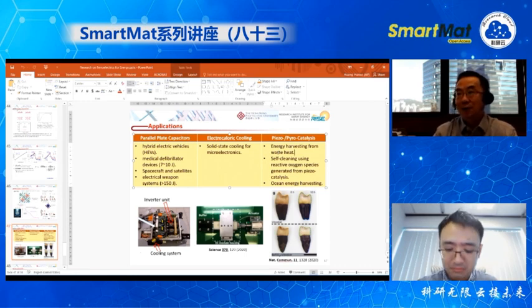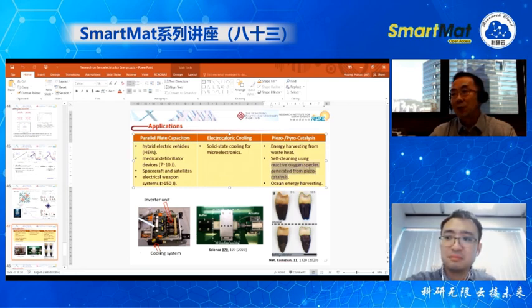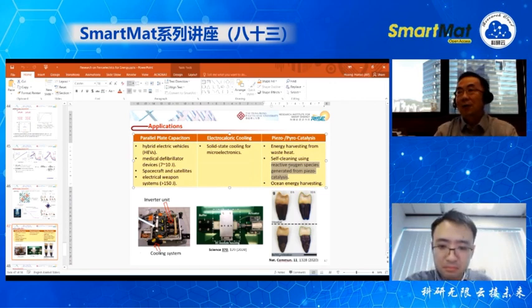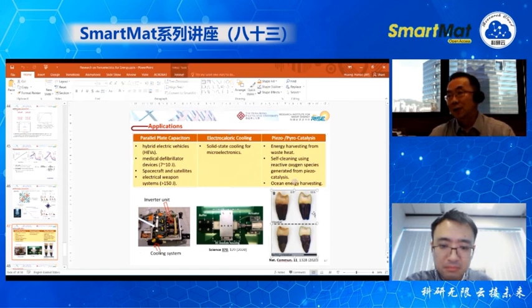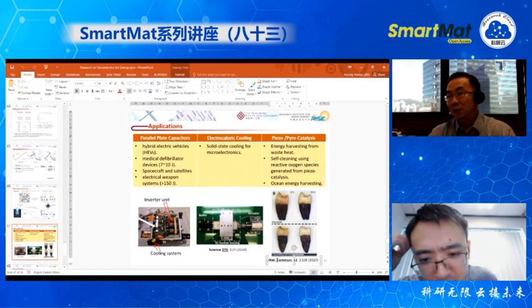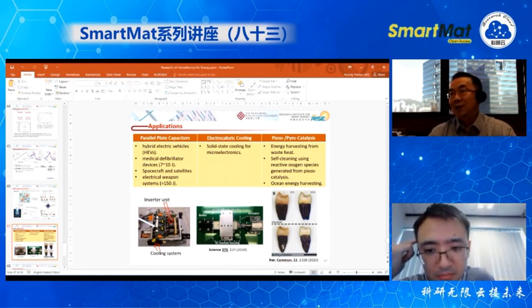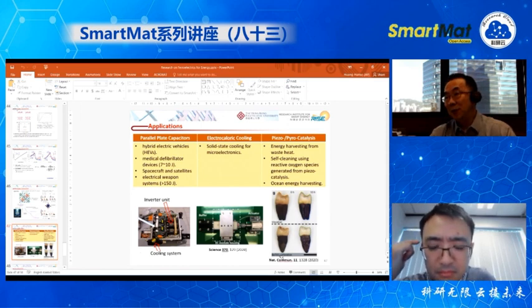So you can forget about hydrogen evolution or water splitting applications because it is not efficient. But we can make use of reactive oxygen species generated from the vibration of the surroundings. Making use of the surrounding vibration, we can generate some reactive oxygen species, and those materials can be used for self-cleaning. Here is an example shown by Professor Wang Yaojing from Nanjing. They use barium titanate to clean teeth. You can see a comparison between the teeth with barium titanate and without it.